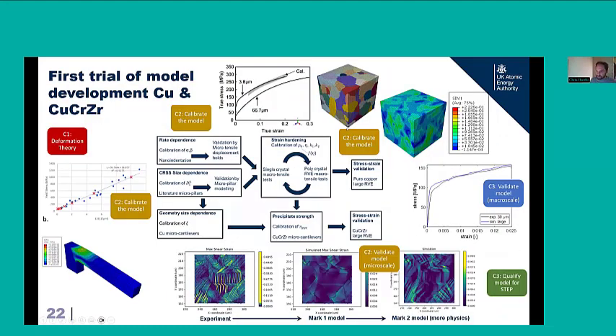And then finally, this is just putting all of that together. So stitching all of that capability together, and we've done an early proof of concept of how we take the single crystal data, how we take the polycrystalline data and develop systematically a calibrated model through to prediction of macro scale properties. To the very right hand side, we've got a stress strain response from experiment, and we've got a simulation, and they to some extent agree. However, what I would say is this is extremely early days for us, and there's plenty more that we can improve upon here.